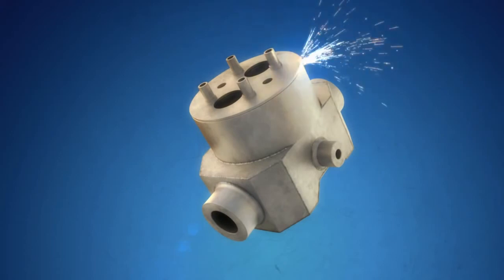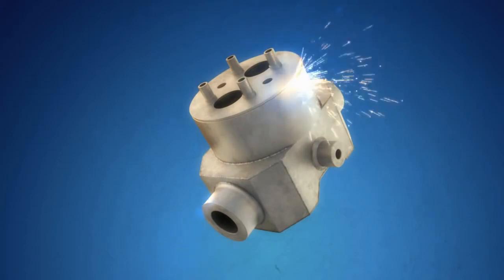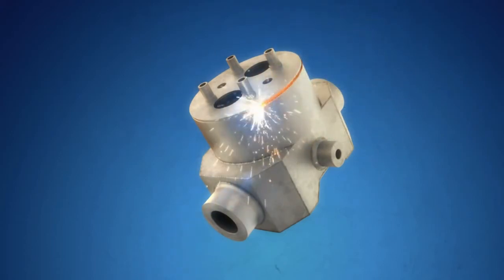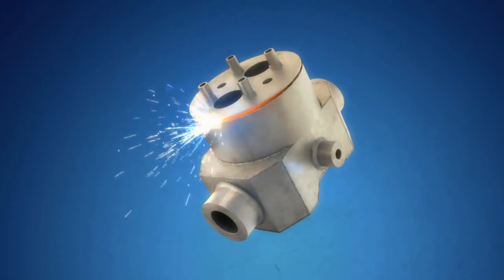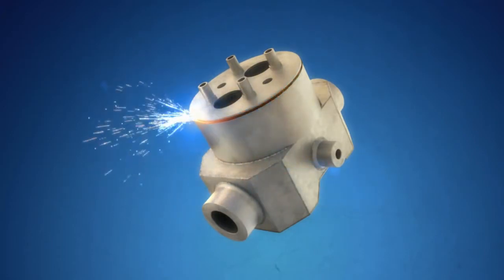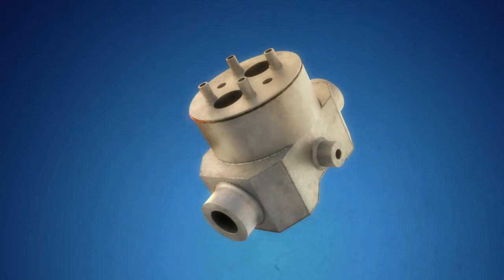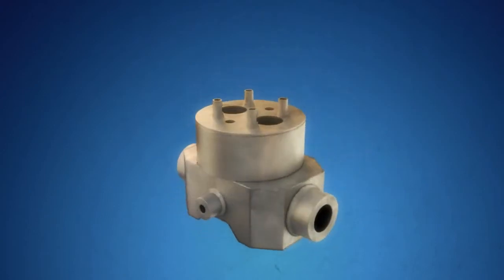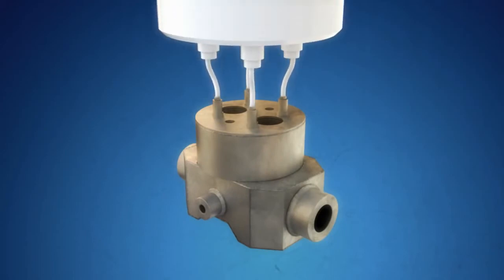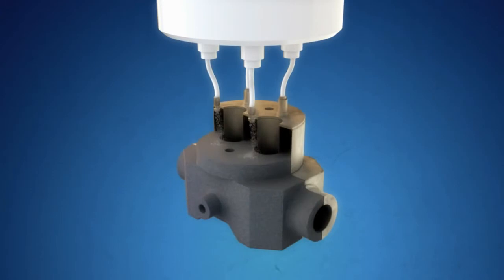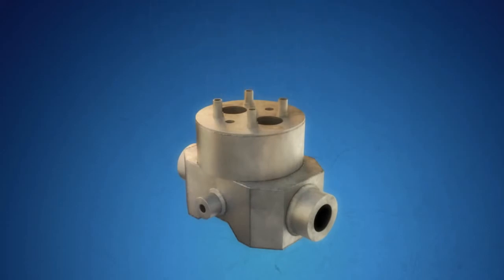The capsule is made by forming and welding sheet metal. The tightness of the finished capsule and its welded joints is verified by testing with helium gas. The capsule is filled with metal powder according to a pre-calculated weight. The powder is packed by vibrating the capsule. After filling, the capsule is again tested for tightness with helium gas.